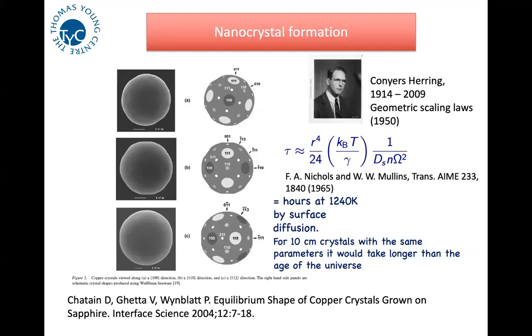And he showed that such an annealing by surface diffusion will always go as the 4th power of the length scale. And if it's volume diffusion, because of course, before you realize that surface diffusion is much faster than volume diffusion, if this was doing things by volume diffusion, then it would go as the 3rd power of the length scale. And he showed this in about 10 lines by purely dimensional but physical arguments, which I thought was a really nice paper. You know, the old papers are much easier to read.